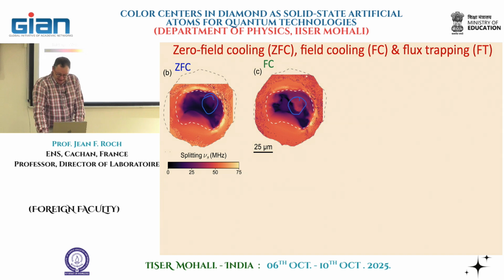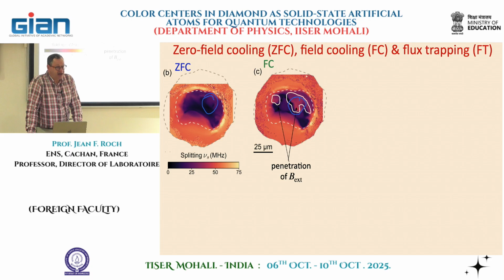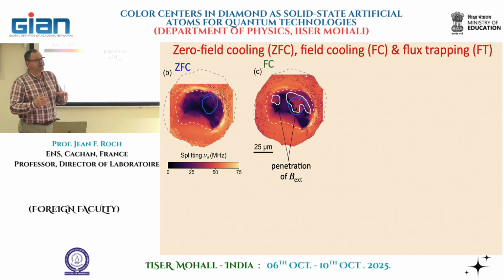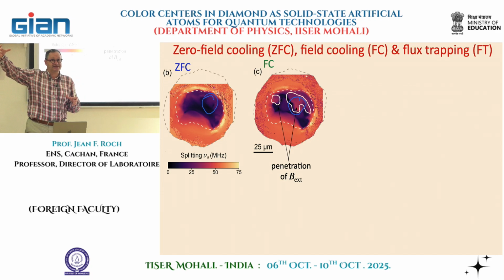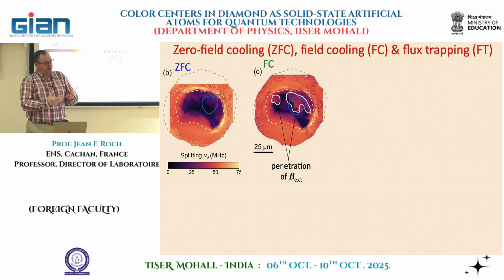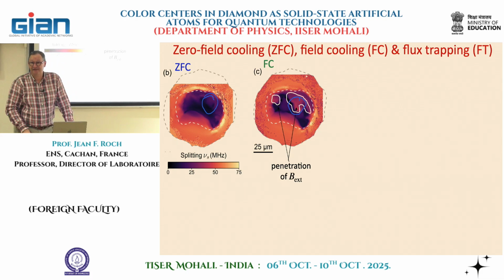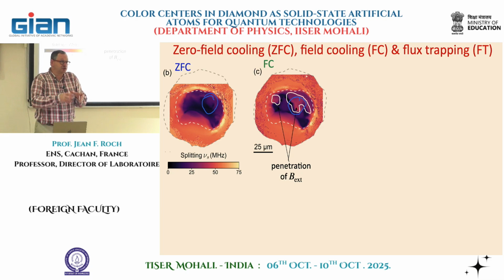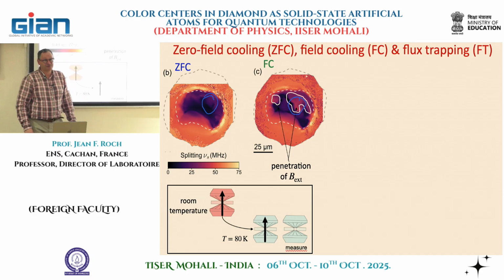And the reason for that is that if there are inhomogeneities in the sample, the magnetic field that is applied during the cool down can already penetrate into the sample and somehow create little zones where there won't be the Meissner effect. And this is what you observe here. This can be due to trapping zones where the magnetic flux gets trapped. And so you can confirm that by a third experiment, which is called the flux trapping experiment.